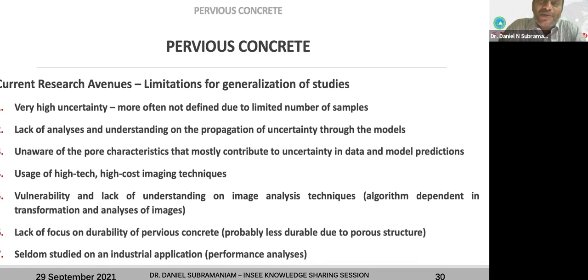So what we have at the moment is a lot of uncertainty around that. One study will have a model which will not be used by another study, because it depends on the sizes of aggregates they used, the characteristics of aggregates, the aggregate shape, size, and distributions. That is one of the things making the generalization of models very challenging, along with the lack of analysis and understanding of the propagation of uncertainty, which is very important for researchers and also for proper application in the industry. Also, researchers are unaware of the pore characteristics that mostly contribute to the uncertainty in data and model predictions, and they use high-tech, high-cost imaging techniques, which are actually not helping, rather than having a big system in place.